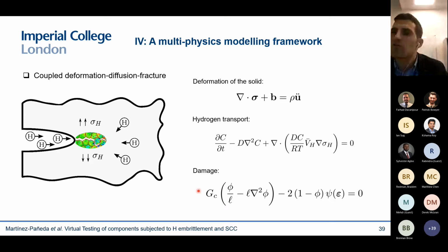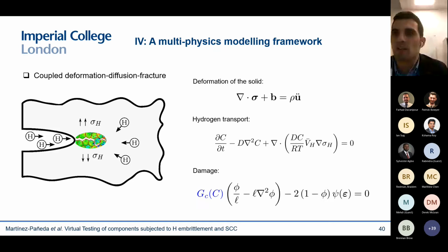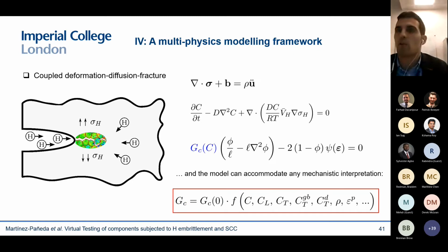But how does the hydrogen affect the damage process? So the way to do that is quite straightforward. You will basically define the toughness of your material dependent on the hydrogen concentration. And this is a very natural way of doing it, because this is what experiments show you, right? That the toughness of your material is dependent on the hydrogen concentration. Of course, the key question is what kind of degradation function do you define, right? How do you degrade that toughness as a function of hydrogen concentration?